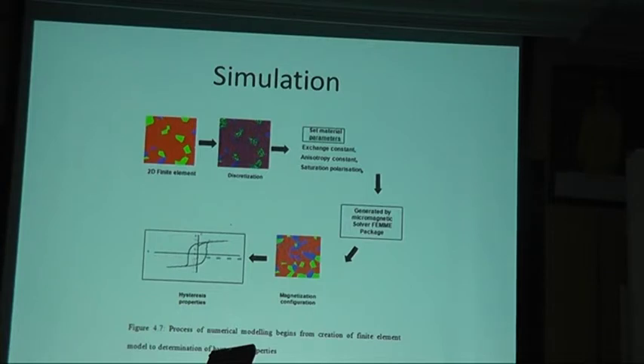After generating using that solver, we get this magnetization configuration. We can see clearly here the magnetic moment in every single grain. Then we can convert this into the hysteresis properties. Just imagine if I wait for 3 months for the solver to generate, and at the end of the day I used the wrong parameter, I have to start all over again. Even though the modeling looks simple, we have to be really careful about the parameters that we put in.